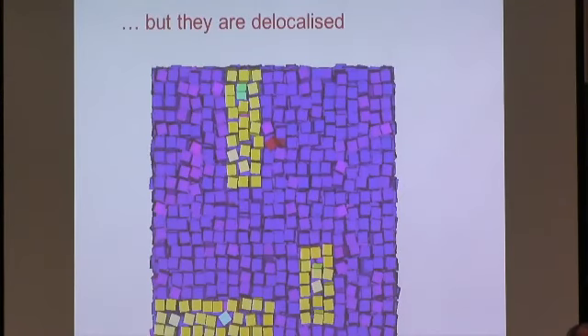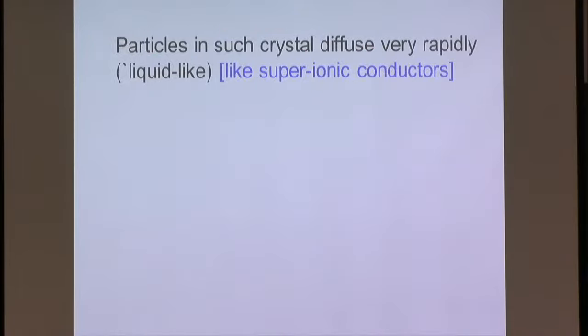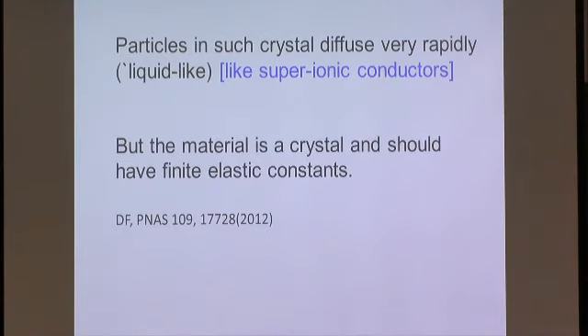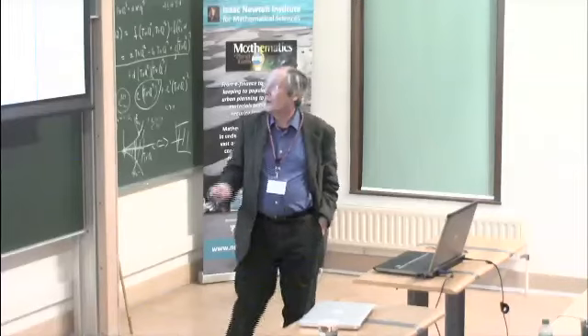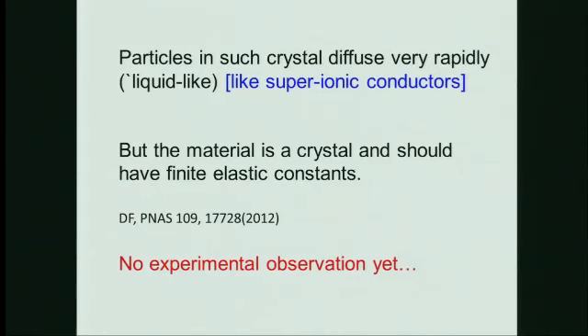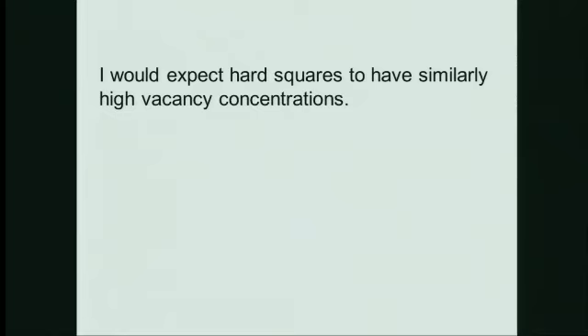And actually, to me, this is another liquid crystal problem, because the length of these things, how long should they be? Well, they can't cross another one. So it's a bit like a liquid crystal model, the Onsager-like model of rods that are perpendicular but can't cross. And I think that all systems where lines can slide like this should show similar behavior, but at the moment there's very little evidence yet. So particles can diffuse very rapidly because of these lines. The material is a crystal and should therefore have finite elastic constants. And as before, there's no experimental observation yet, at least not to my knowledge.